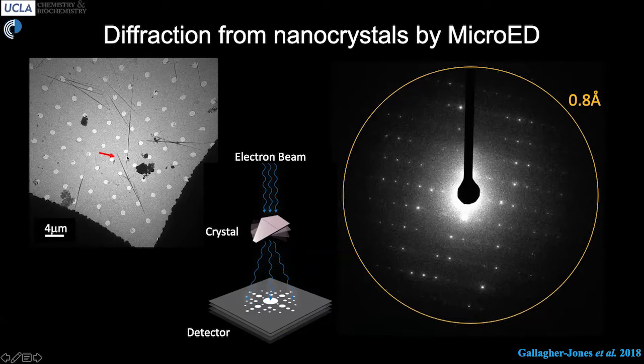And so we tried to identify a region on the scale of about a micron to illuminate with the electron beam and selectively collect diffraction from that region. You can see on this carbon film there are many tiny holes. Each of those holes is about a micron. That means the thickness of this needle is only a few hundred nanometers. The entire illuminated area is shown here in this slightly darker gray color. That was the area that was illuminated by the beam.